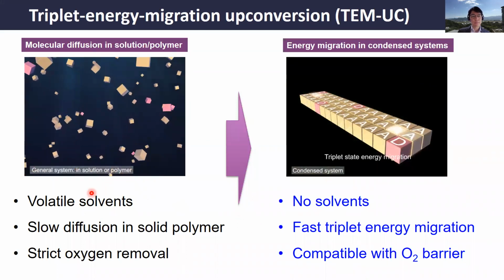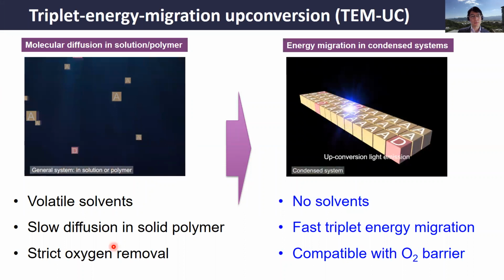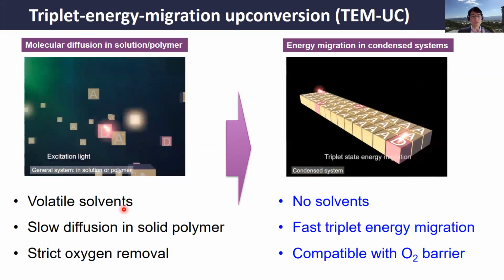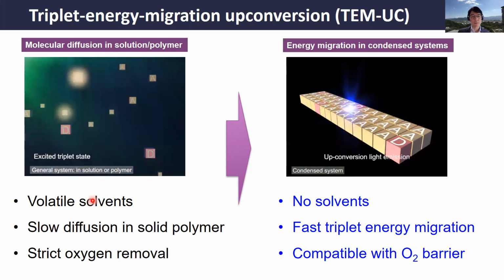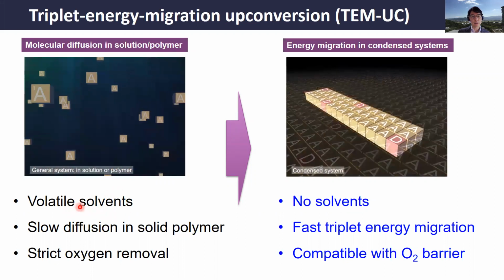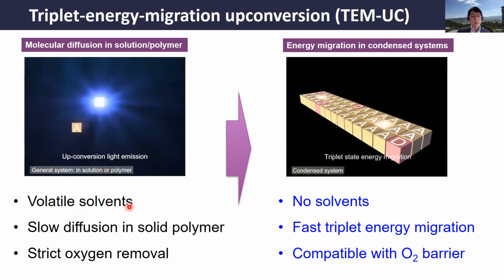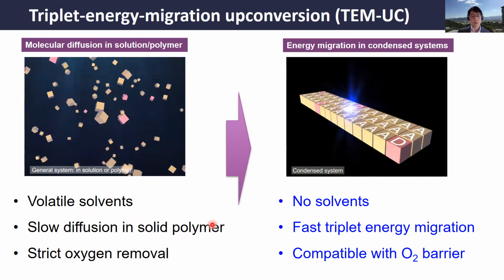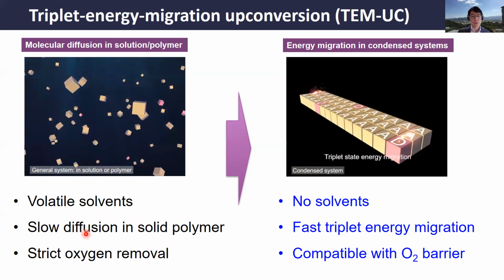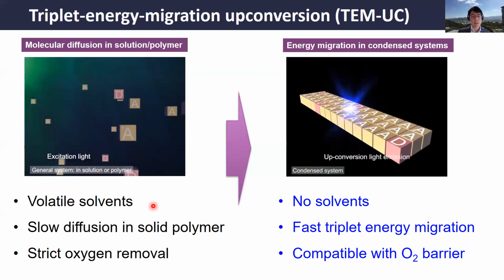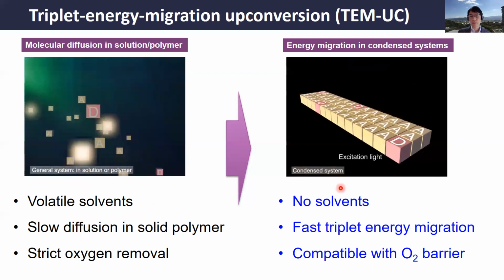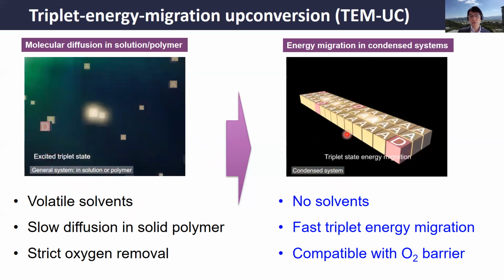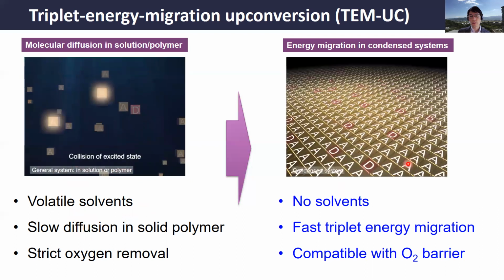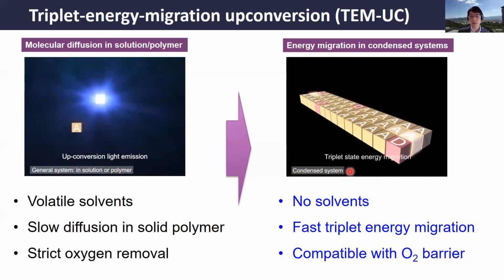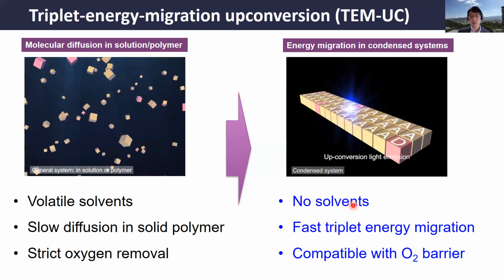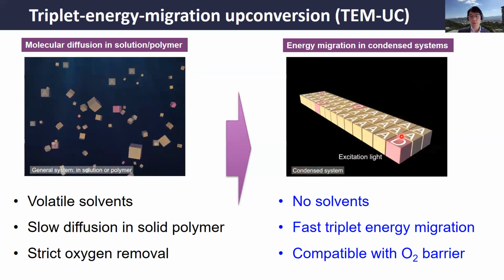Because we see a few severe problems in this molecular diffusion-based upconversion. Of course, you need a fast diffusion constant of molecules, so you need to use volatile solvents with low viscosity. You can use soft polymers, but in that case the molecular diffusion is not as fast as in solvents. To solve these issues, we have been proposing to shift to energy migration or exciton diffusion in condensed systems, because now you don't need any solvents, and you can also get fast exciton diffusion in the dense assembly.